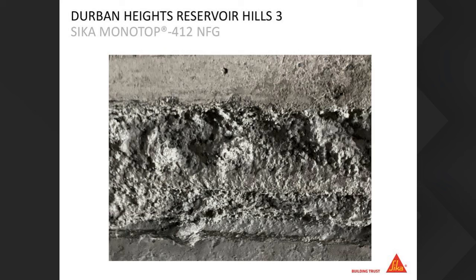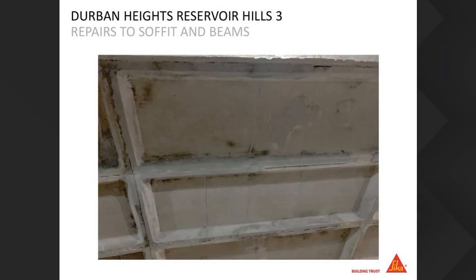Here you can see a dense wet spray application in layers. You can see now the rough texture. So when the following layer follows in the spray application, you don't only get a mechanical key, you get the chemical key bond and then the mechanical that goes with it. Just some of the panels that's been repaired. If you look top right on all the beams, that's the finishing product.